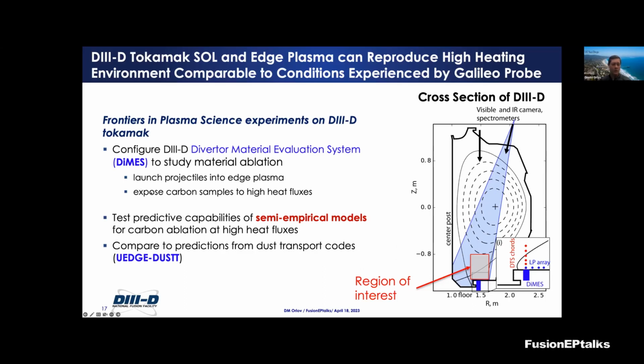We were thinking about two types of experiments: launching little projectiles into the plasma edge, or exposing carbon samples to high heat fluxes. What we wanted to do is take those semi-empirical models, the models that were created after the Galileo mission into Jupiter, and test those models to see whether they stand, whether they confirm our observations in regimes close to the Galileo probe's entry.